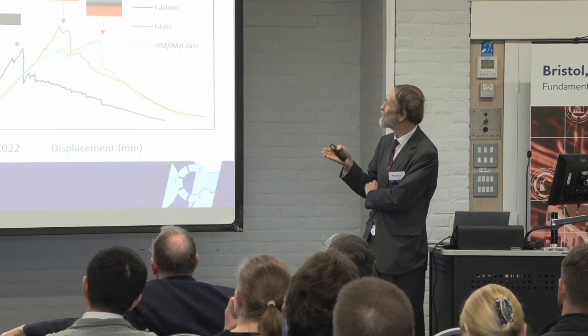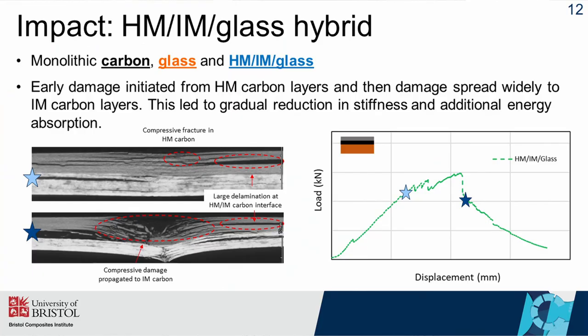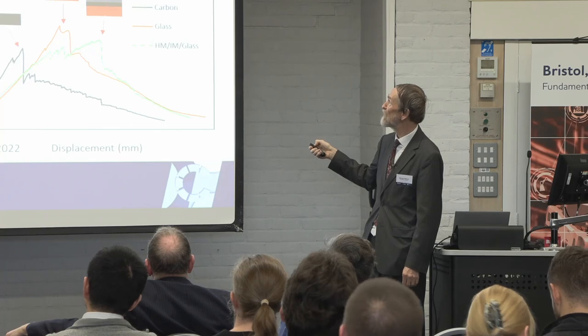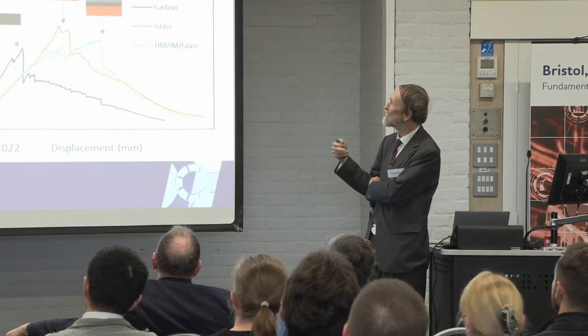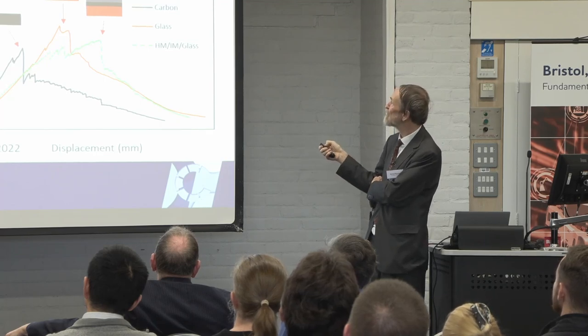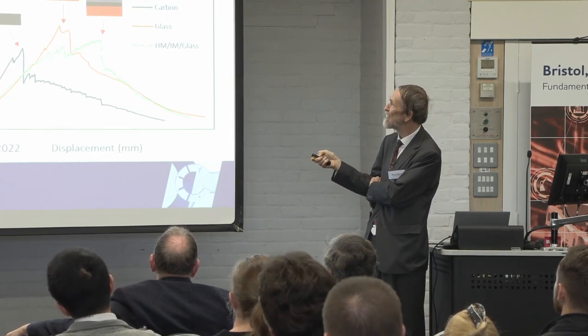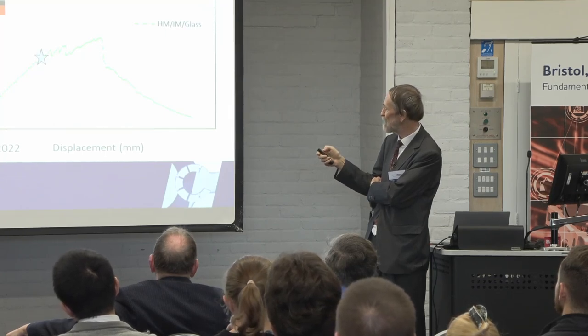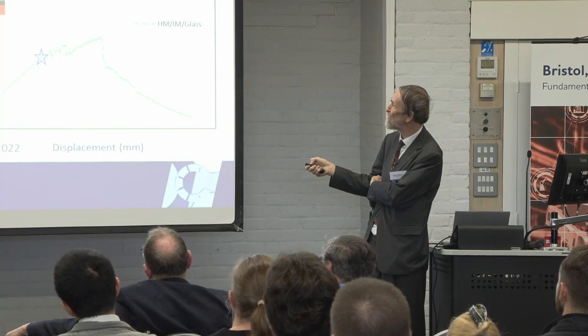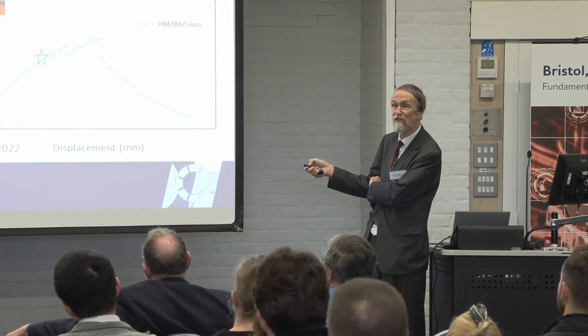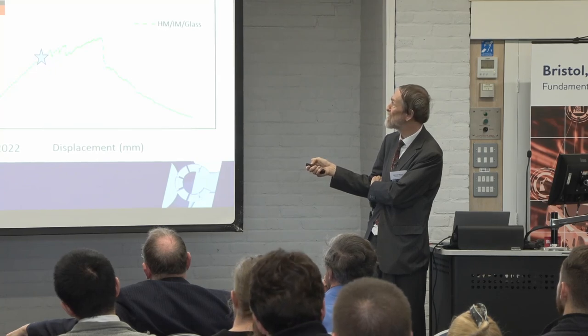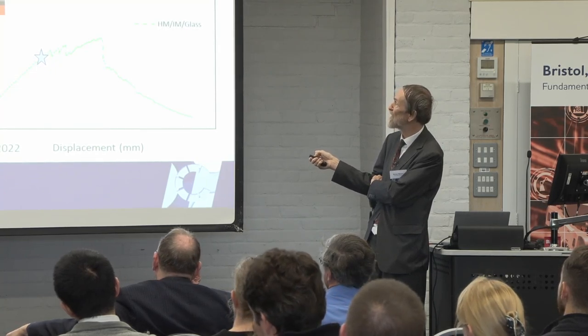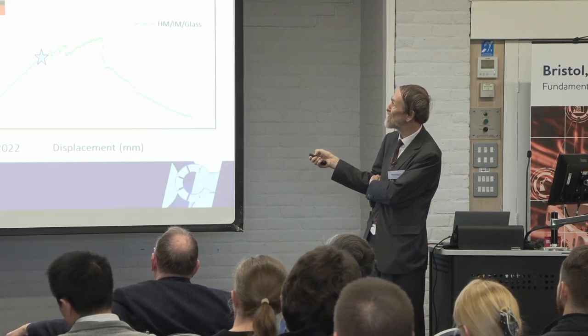Let's look at another case here where we've compared the basic carbon and glass with a hybrid where we've got different grades of carbon. Here we've got a high modulus carbon and an intermediate modulus carbon on that face there. What this does is it makes the failure a bit more gradual. Because we've got the high modulus carbon on the surface, we actually get a compression crack a little bit earlier. So we get a compression crack on the surface, but because we only have the high modulus on the surface, it doesn't propagate right the way through the thickness. So we get initial failure first of all, but then we get a bit more gradual failure as this progresses, but not catastrophically.